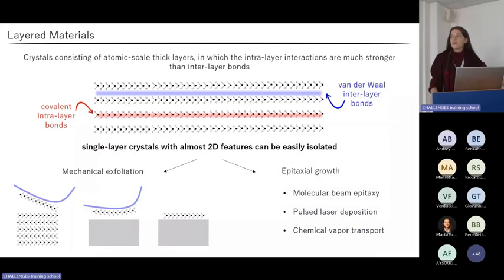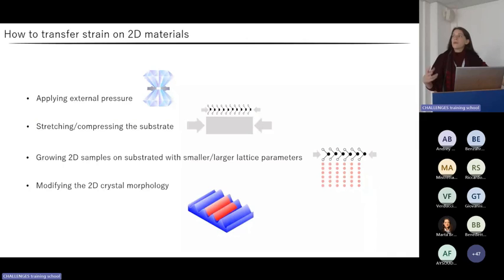The most common technique to do that is mechanical exfoliation, first performed on graphite back in 2004, which provides us with very high quality few-layer flakes, but which unfortunately is not scalable. For this reason, epitaxial growth techniques have also been implemented, which allow obtaining large area, low-dimensional samples. Due to their atomically thin nature, monolayer or few-layer crystals in general display a much stronger deformation capacity compared with their bulk counterparts, which makes their properties highly tunable by strain application.